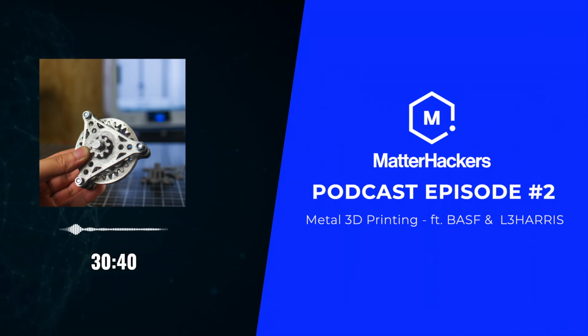We also noticed that shrinkage can occur in the printed part and also needs to be considered for debinding and sintering. So we see that in our chart here, that just because we think the green part size, especially the height, should be a certain dimension, we're finding out that it does shrink a little bit in the machine as we print them. And we also know that it needs to increase for tall parts over small parts. Next slide, please.